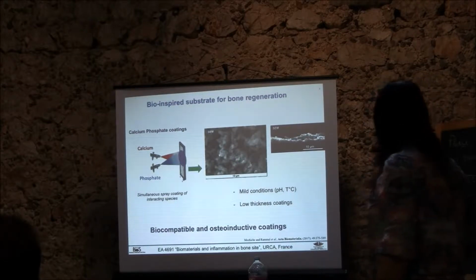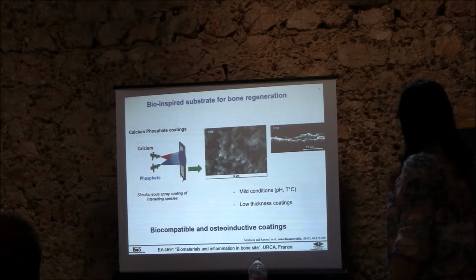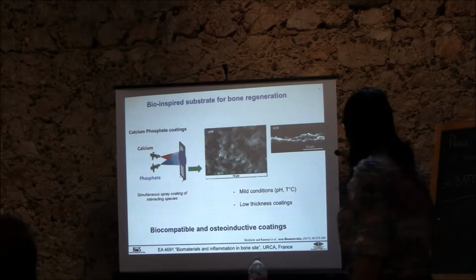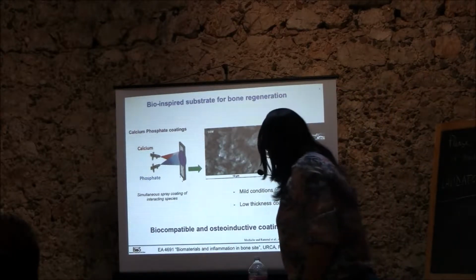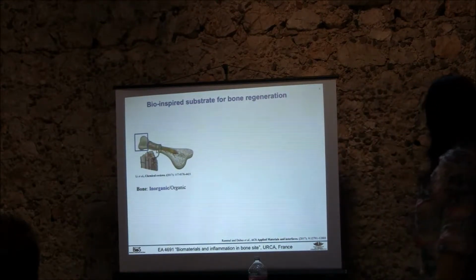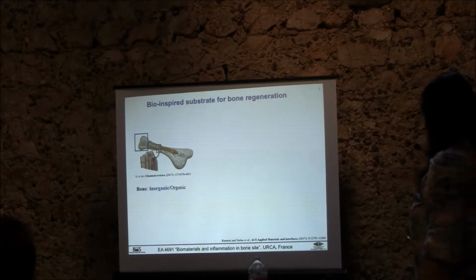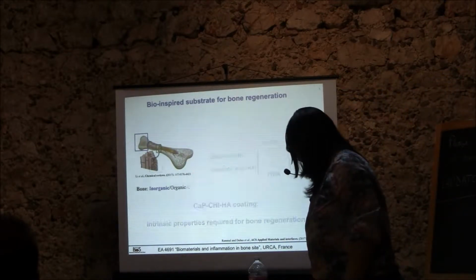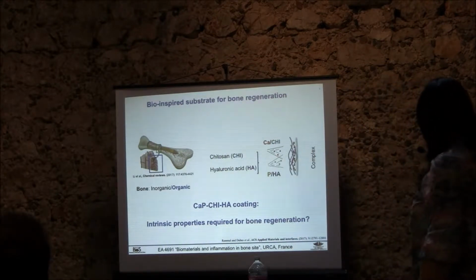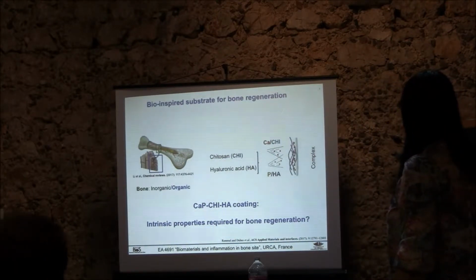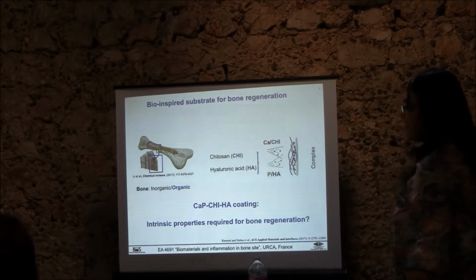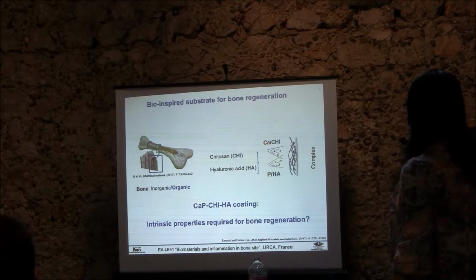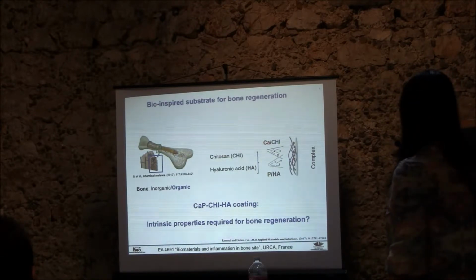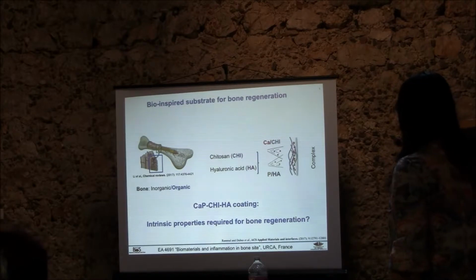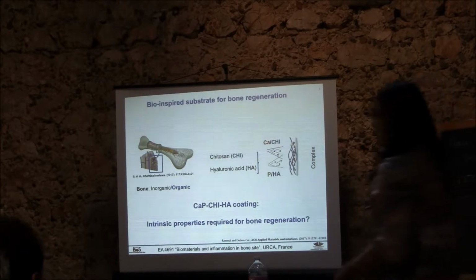This calcium phosphate coating was biocompatible and osteoinductive. However, bone is a hybrid material composed of an inorganic and an organic matrix. So in our lab, we tried to build a hybrid coating by introducing chitosan and hyaluronic acid. Chitosan is positively charged, reacts with negatively charged hyaluronic acid, and forms a complex.